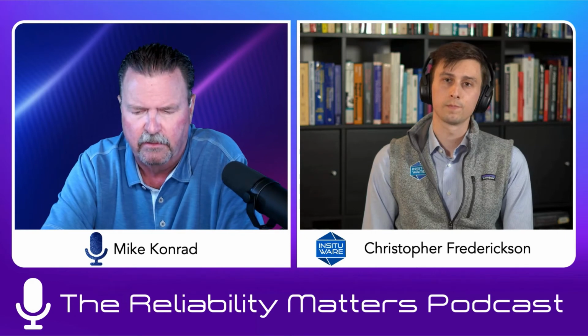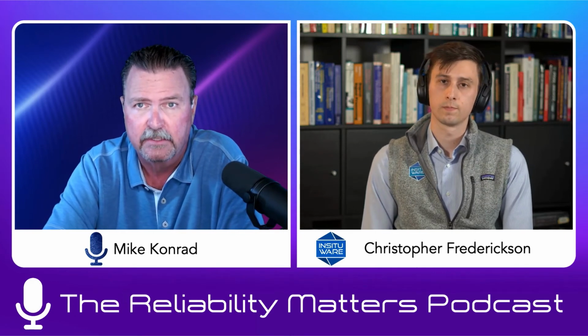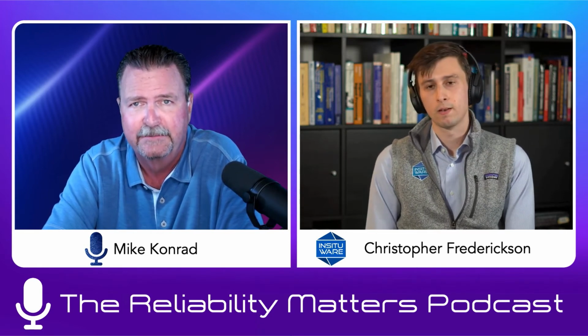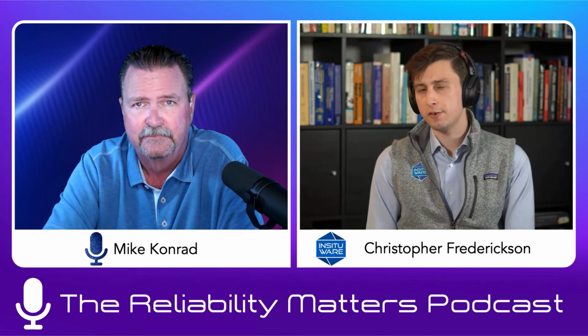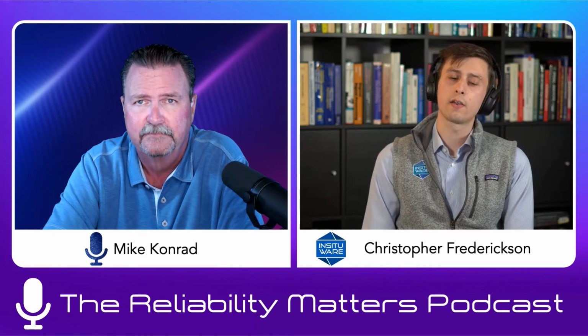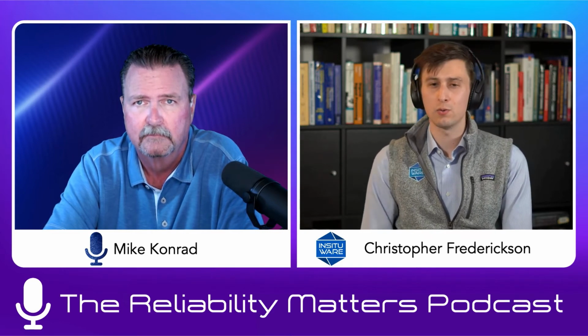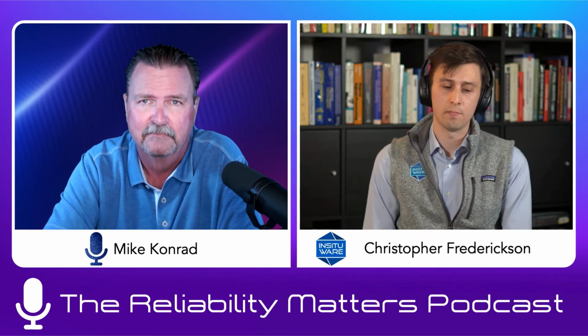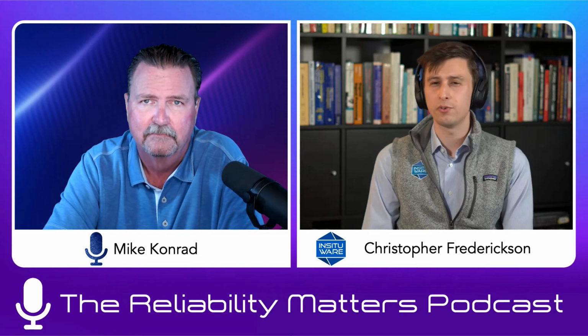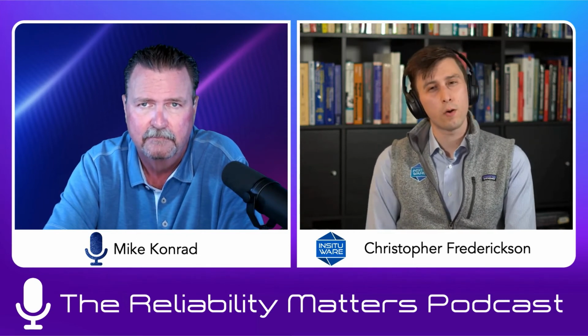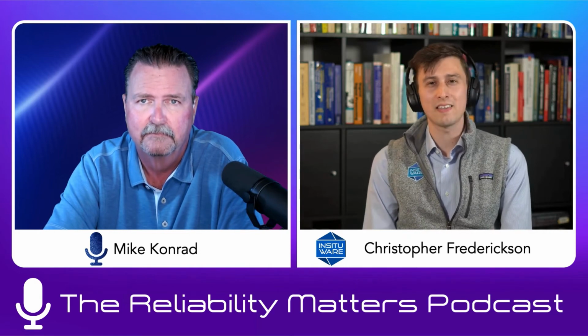And are you able to measure or evaluate any type of conformal coatings, from acrylics to silicones to parylenes to anywhere in between, or is it a specific species of conformal coating? There are some limitations with the technique. For parylenes, you can't really make a measurement of that base material initially, so you're not able to measure parylene coatings. Some silicones are a little bit too resistive to make that measurement, and you're not really thinning them in a lot of applications. So urethanes and acrylics are most common and kind of best for this application. Epoxies as well can be used.